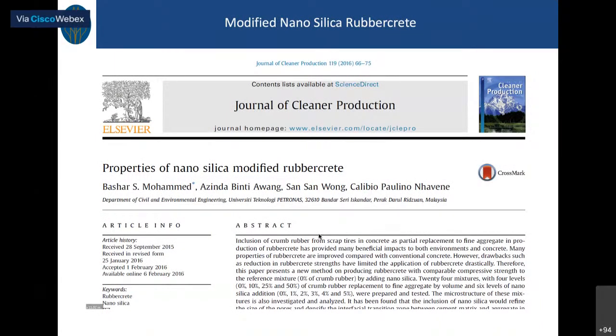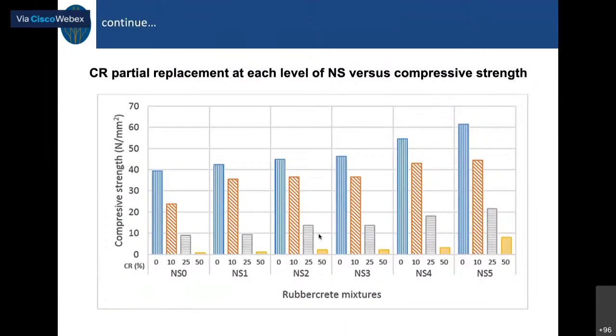And also we did a study. If you say, okay, I don't want to use it because it will reduce the strength, I want a high strength rubbercrete. So we used nanosilica. The nanosilica has two effects: the chemical reaction with Ca(OH)2 produces the gel, which is responsible for the strength, and it can also fill all the nano voids inside the microstructure of the rubbercrete. So it densifies the ITZ between the hardened cement paste and the crumb rubber, and also increases the compressive strength.